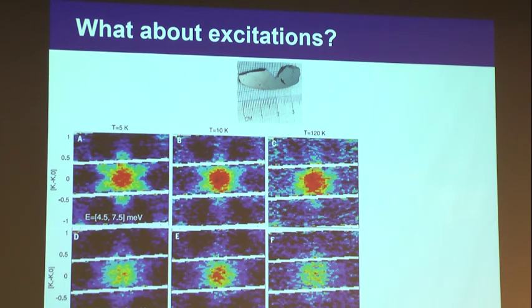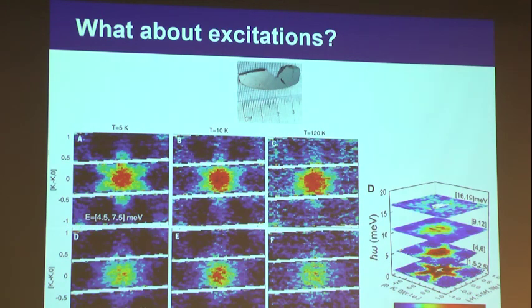And unfortunately, that's not what we had, but these guys at Oak Ridge were able to grow large single crystals of ruthenium chloride, and they were able to do inelastic neutron scattering work on that. And again, this is a really competitive field. Another group in Korea did a similar type of inelastic neutron scattering work on the ruthenium chloride, and they essentially show a similar magnetic excitation spectrum.